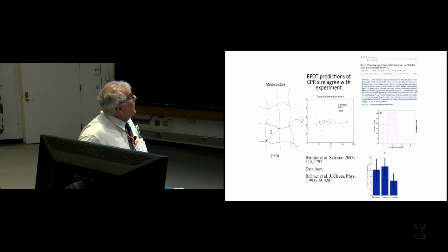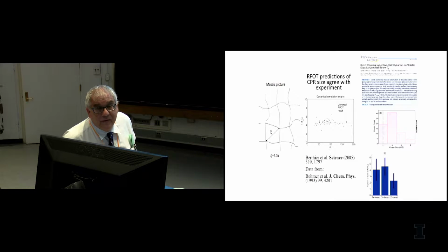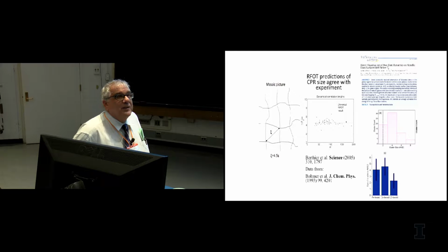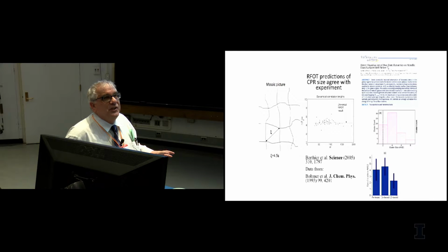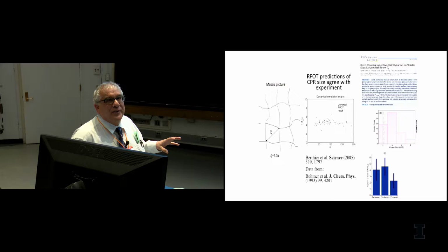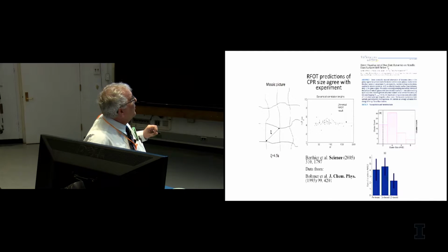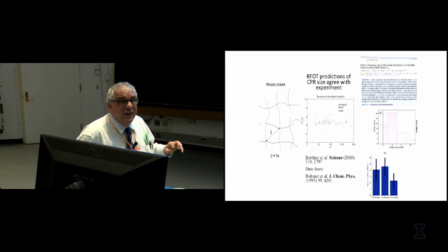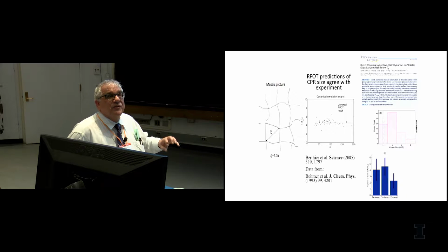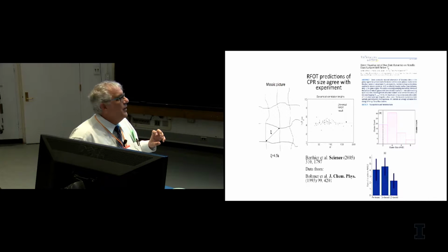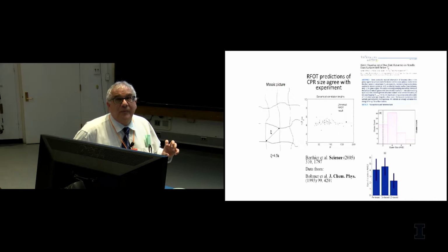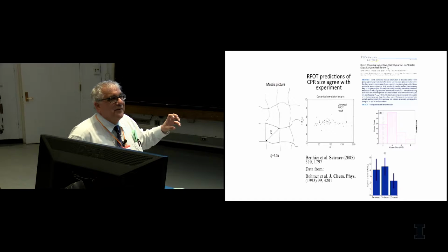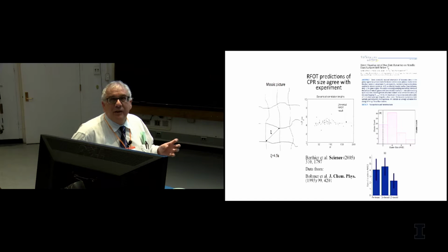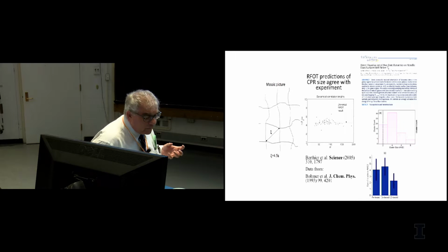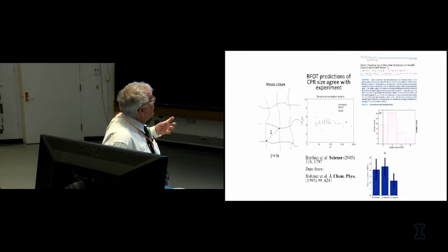One of the other characteristics of this, then, is because the surface energy at Tg is a more or less universal thing through this entropy loss of localizing to a Lindemann length, the size of a region which is flipping over and changing structure is actually fairly universal. It's 4.5 in the theory times the size of an individual bead or particle.